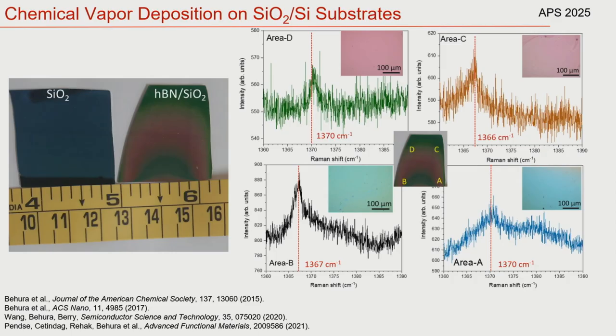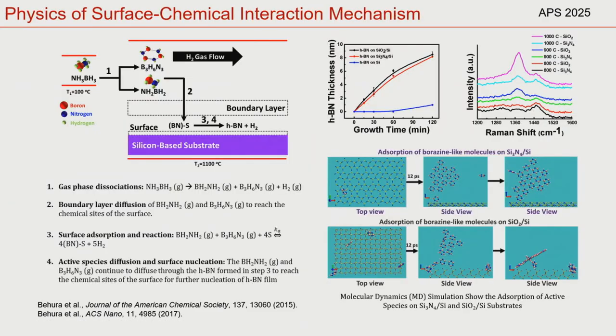And another thing that's great about having this dielectric substrate is that we can then take this readily deposited hexagonal boron nitride and create heterostructures if we so care to, as my previous speakers mentioned, or we can just directly integrate it into circuits. Now, how exactly does this work? We know how catalytic interactions occur, so we need to propose mechanisms as to how we can directly deposit hexagonal boron nitride. So we utilize interactions between the boundary layer.